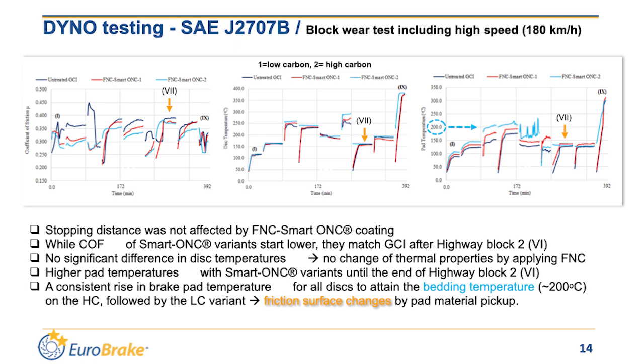Figure 2 shows that the disc temperatures were not changed, which indicates that there is no change in the thermal properties after applying FNC Smart ONC. Figure 3 shows that the highest value of pad temperature was obtained on the Smart ONC variants until the end of highway block 2.